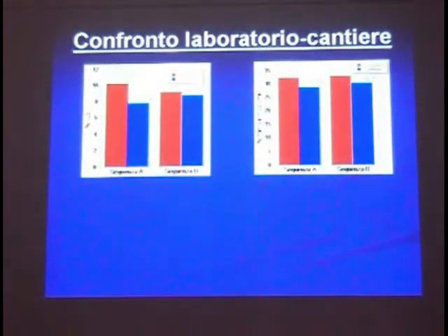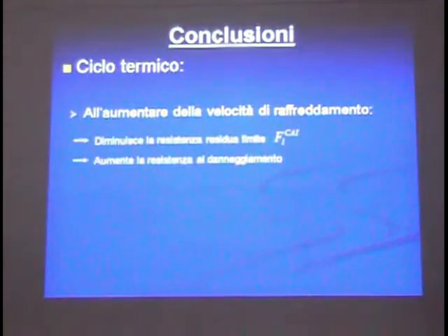And this is due, and this is the very last slide, mainly to the fact that although they have a considerably lower void percentage, they also have considerably less matrix inside. So there is probably some lack of the matrix, which results in a reduction of the interlaminar fracture resistance.